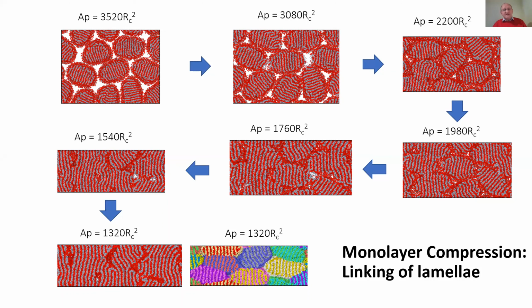As you can see, we have an elongated shape of the microgel on the surface. And the reason is pretty simple. It's a competition of two symmetries. The lamellar structure wants to form stacking, and this contradicts the spherical shape of the microgel. If the flexibility of the lamellae is not so high, this effect dominates, and the lamellar structure is more or less parallel within the particle, which forces the particle to deform.